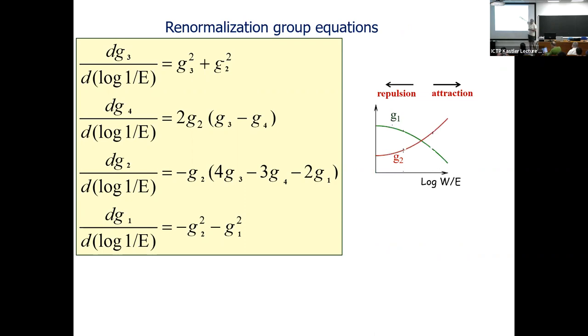This is a bad guy, against pairing. This is a good guy, for pairing. I want to make the good guy more repulsive than the bad guy. This is what this equation does. I'm not making this up; it just follows from the equation. You start with repulsion and keep going, and you can do this because couplings are small, but couplings times logarithms are of order one. And you see that the good guy goes up, the bad guy goes down.